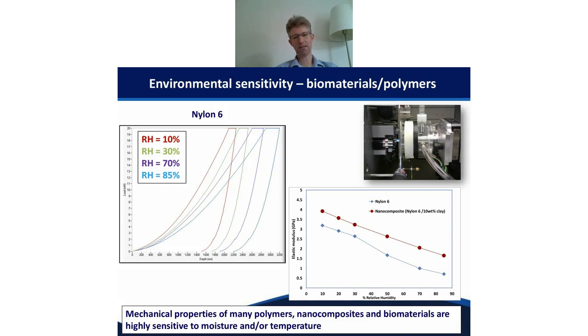And in this case, as the test has essentially gone from dry and then moisture's gone in, we can track how that material, in this case nylon, because it's hygroscopic and very sensitive to the ingress of small water and organic molecules, is plasticized by that, and it gets less hard and less stiff. And you can see in the graph here how its stiffness decreases as a function of increasing humidity.